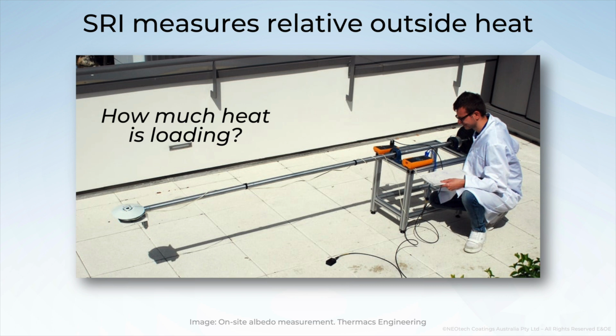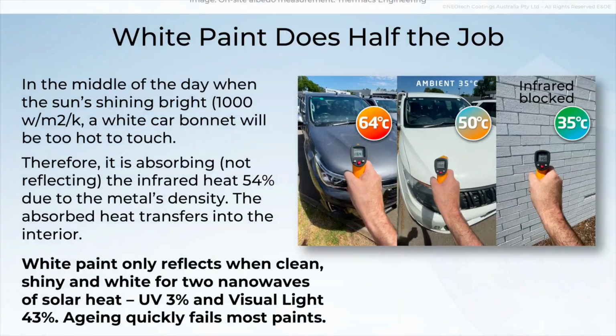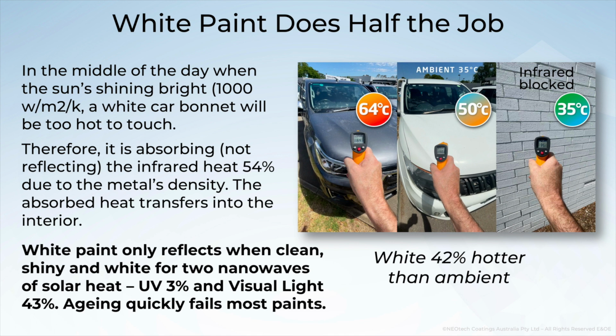See, solar reflectance, that's why people want to go whiter and whiter. And a way to demonstrate that is, we always use a car as an example. If white pigments were to stop all the heat, then the bonnet or the hood of the car would be near ambient temperature, in this case 35 degrees, but it's not. It's 42% hotter as a white car. So the density in the metal, the infrared heat, is being heated up. It's gone past the white pigments and then it's transferring through. So if you block the infrared heat and then adjust your color, then you actually have a fantastic way to ensure that you don't get heat load on any surface.